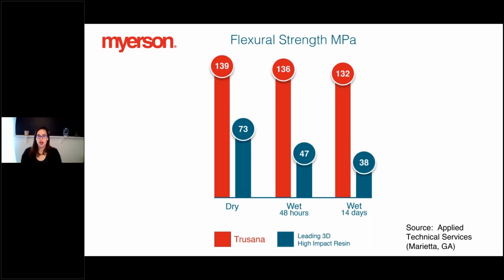Same with the flexural strength. If we look at dry samples of Trusana, we have a flexural strength of 139 megapascals compared to the leading 3D high impact resin, 73. If we move again doing that 48-hour water submersion test and then testing the mechanical properties, the flexural strength pretty much remains consistent at the high 130s.